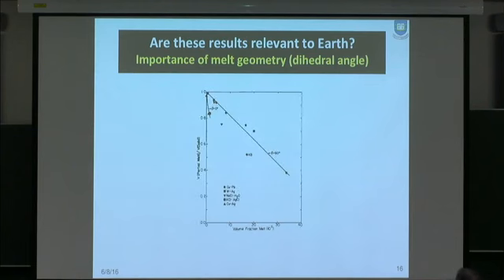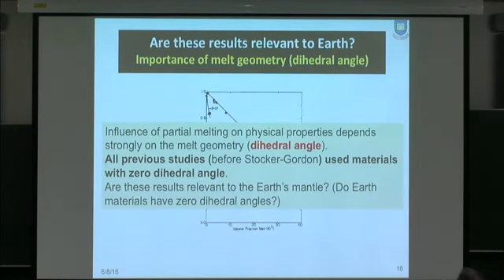But then he did some simple experiments and concluded that the influence of melting on physical properties depends strongly on melt geometry, and all previous studies before Stocker and Gordon used materials with zero dihedral angle. So therefore, if the dihedral angle of Earth material is not zero, those results cannot be applied. So this is a very important statement.